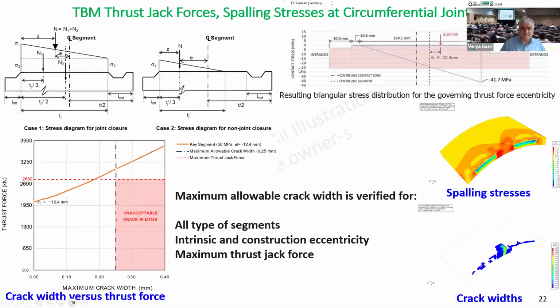So for the spalling, as I said, in the longitudinal joint, you see here, either we have this kind of trapezoidal or triangular distribution when the joint is open, when the resultant of the load is outside the middle third of the segment. You see here, for this particular case, we draw the crack width based on the thrust force. This is the region which is not acceptable, beyond the values which are specified. So you see the spalling stresses between the pads and the cracking, the result of the modeling.